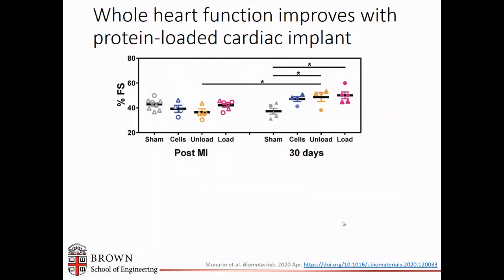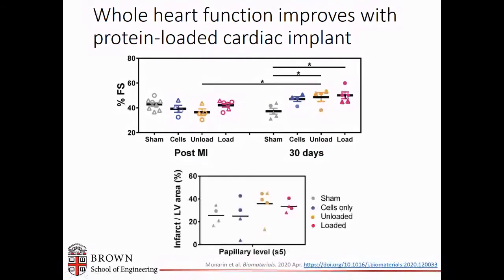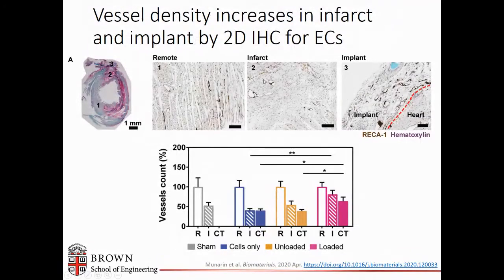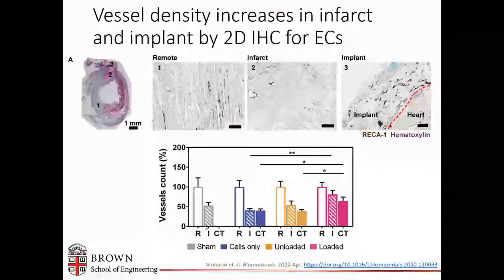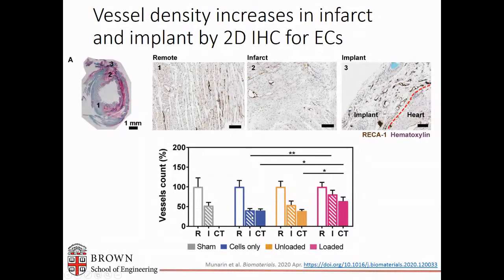In looking at whole heart function by echocardiography at the 1 month time point, there was a statistically significant improvement in function when there were the unloaded and loaded microspheres in the engineered tissues. This was not due to a change in infarct size because there was no difference in infarct size. And when we looked at the endothelial cells labeled here by RECA 1, we quantified their density in the remote healthy tissue, in the infarct, and then also in the cardiac tissue. And what we found was that, as expected, the infarct had much lower vascular density than the healthy remote tissue. And the cardiac tissue had low vascular density as well. But this was improved when we went from an unloaded to a growth factor loaded microsphere. So this was very promising to suggest that the growth factor delivery had an impact on the vascular development.